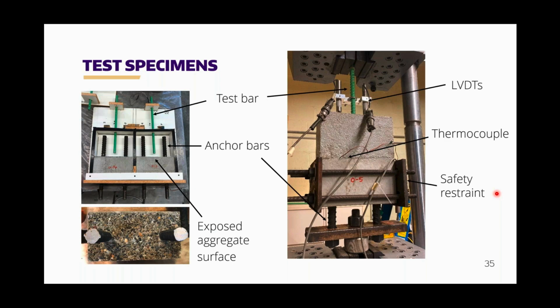Once fully cast, cured, and brought to temperature, you can see the testing rig and the setup on the right-hand side. So we have the cementitious concrete on the bottom with those anchor bars. Those threaded bars are then tied into that steel plate. The HCSC is on the upper portion, so you can see that similarity in color and texture. And the epoxy-coated bar is grabbed in the chucks of the testing machine, and that whole thing is put in